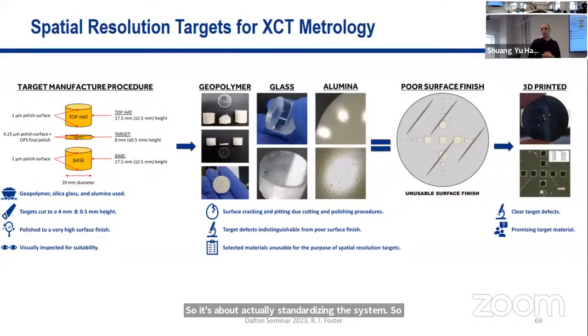So where we're up to on this, unfortunately, we're having some problems. Essentially, developing these targets, first of all, we wanted to start with using the geopolymer itself. The reason for that is to ensure that you've got the same X-ray attenuation of your target in your final material. We then moved on to glass and alumina, all three of which had features larger than the minimal features we wanted to produce with the target. For example, if we want to add a 10 micron feature, but we actually have features already existing in the target of 100 micron, there's no way for us to identify which one is which for final target formation.